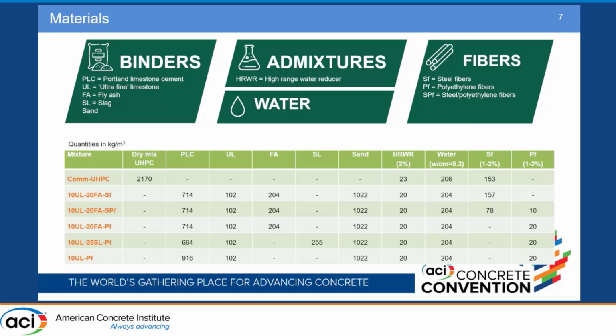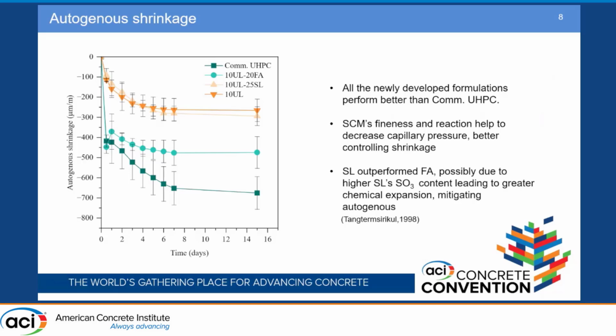What have we done exactly? We used locally available materials. We developed 5 different formulations that differ from each other in the proportion of the binder materials and also in the type of fibers that they use. The first one uses only steel fibers, one is a hybrid system with both polyethylene and steel fibers, and the last 3 use only polyethylene fibers. We kept the water-to-binder ratio constant at 0.2 and the addition of superplasticizer at 2% by volume, and we compared everything with commercial UHPC.